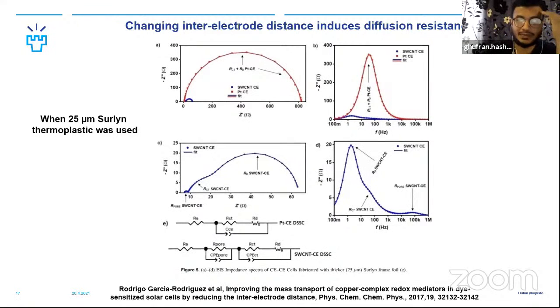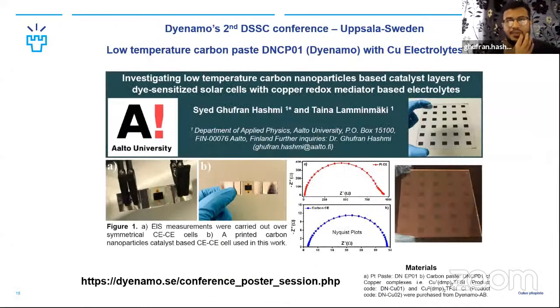So one of the motivations was to replace this with a cheaper, low cost, efficient alternative. So then I tested very quickly the screen printable paste from Dynamo and compared it with a screen printable paste of platinum for the conference at that time that was announced by Dynamo. And you can see here, we just presented through a poster presentation the impedance response of both types of catalyst material loaded with the copper electrolyte.